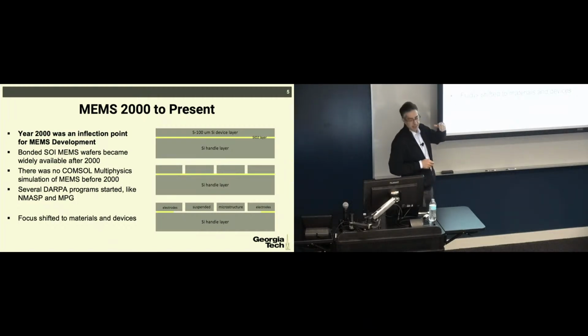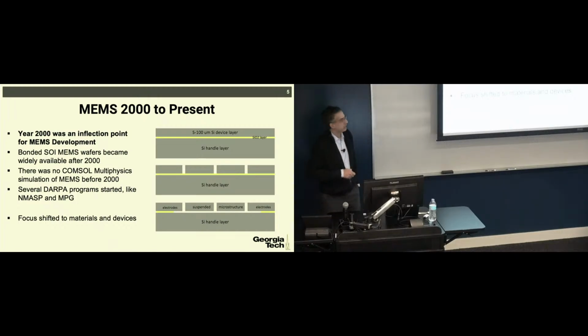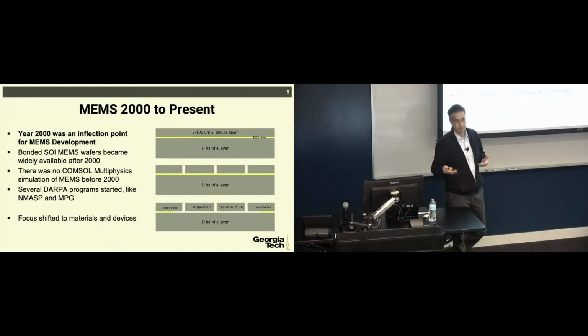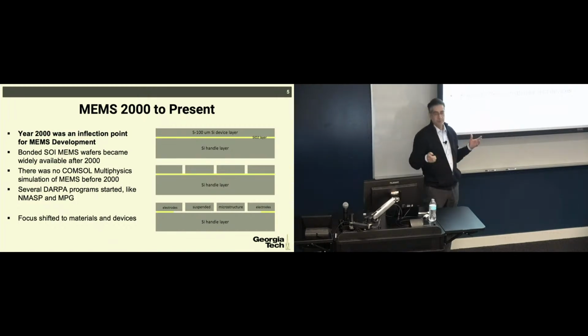The bonded SOI, the nice thing is that you can actually get to any type of thickness of the device layer that you want, anywhere from 5 to hundreds of micron. And you can also tailor the thickness of this buried oxide layer, okay? So you would go and order this online. So there are, even to date, companies that you can get your custom-made SOI wafers with any type of silicon handle and device layer, regardless of the doping. You can have all sorts of doping that you want to have, even highly doped 111 silicon versus 100 silicon. You can choose the thickness of the oxide layer.